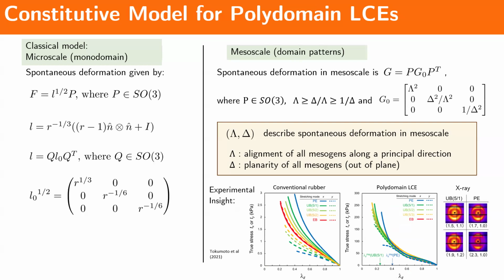These are people in Japan doing really careful biaxial experiments on rubber materials, on LCE as well as on conventional rubber. They impose two different biaxial stretches on the material. In a regular rubber, when you do two different biaxial stretches, you would get two different, unequal principal stresses in the two directions. But what's interesting is that for this polydomain LCE, you can impose two different principal strains, but you end up getting the same two principal stresses up until some value.